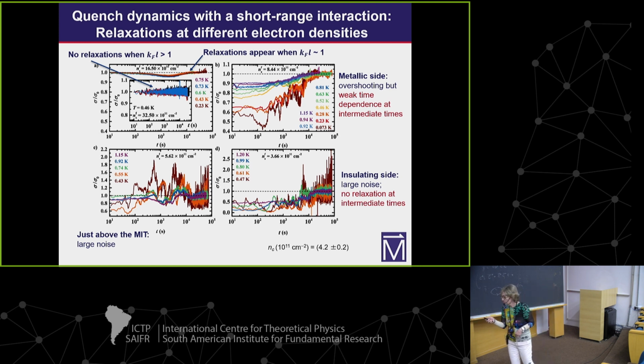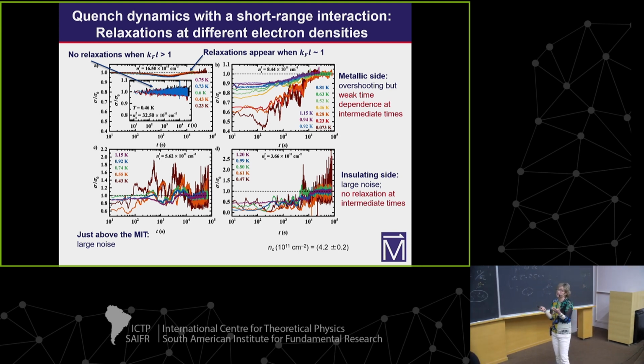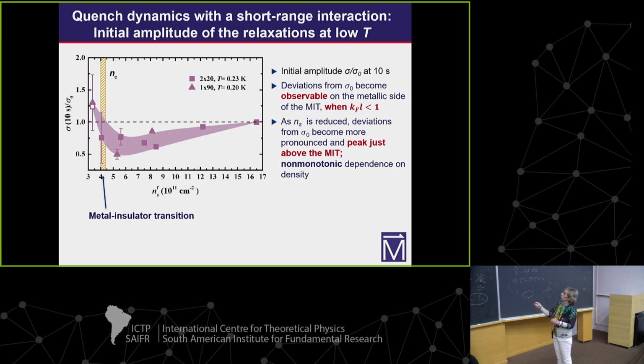So in order to try to extract some kind of density dependence, something quantitative out of this, we fixed the temperature and looked at the deviations, initial deviations from this equilibrium value. So this is what's plotted here: at 10 seconds, the deviation from the equilibrium value as a function of density, at a temperature of about 200 millikelvin.